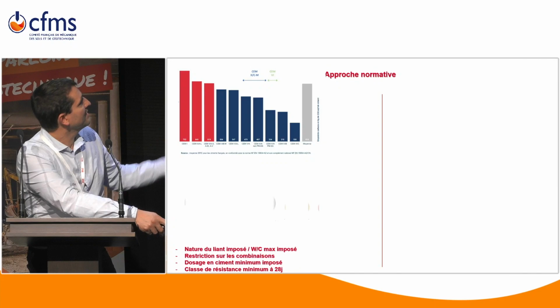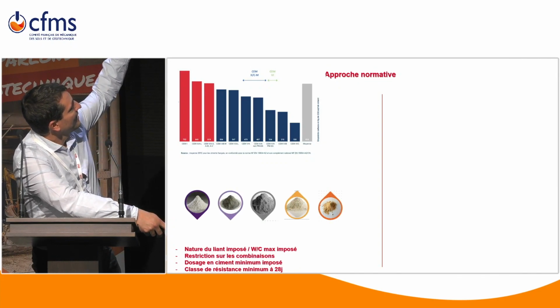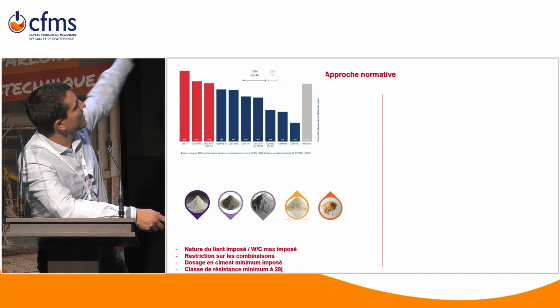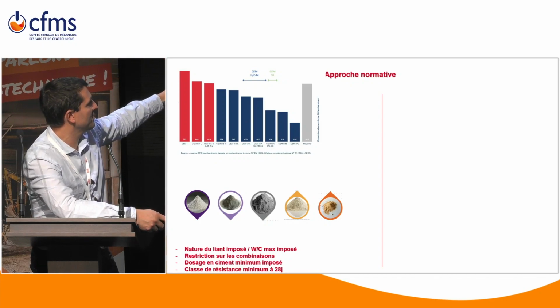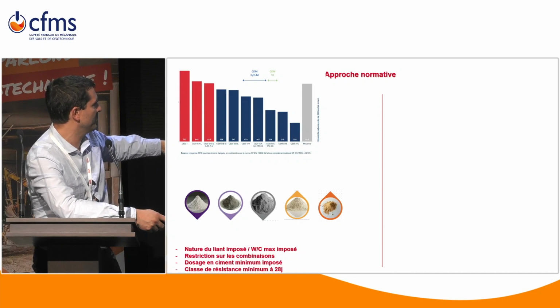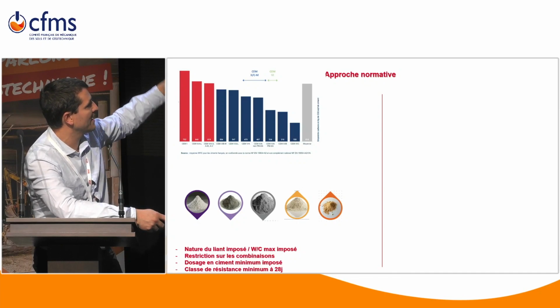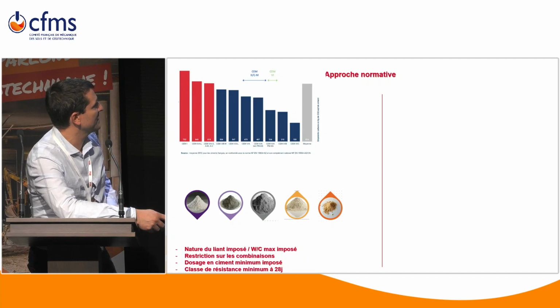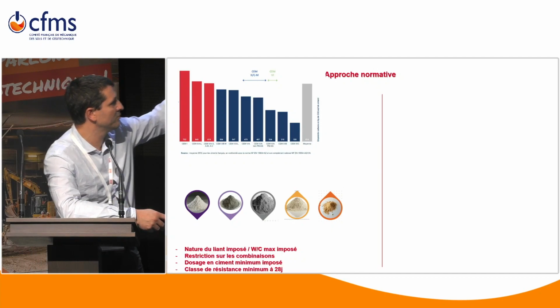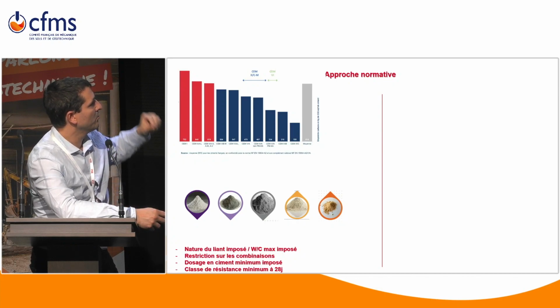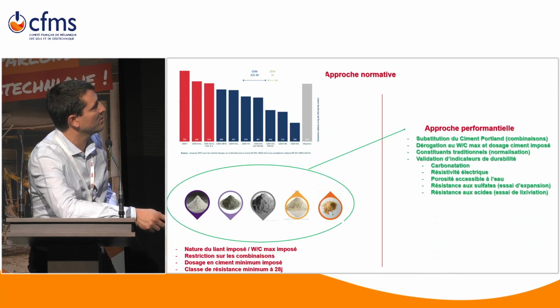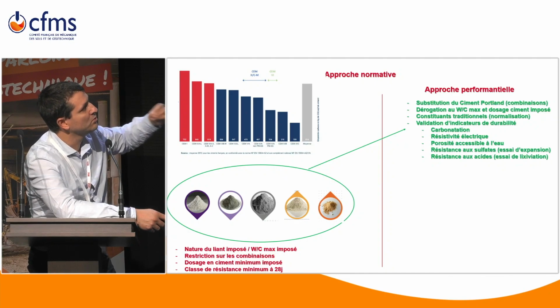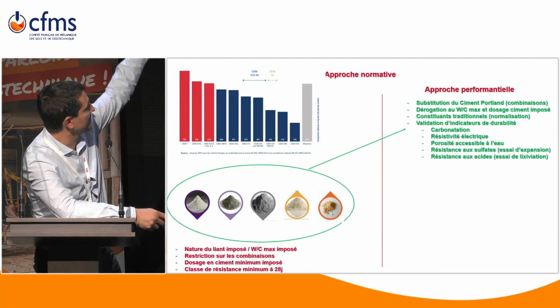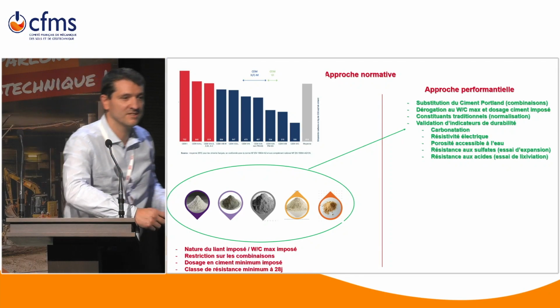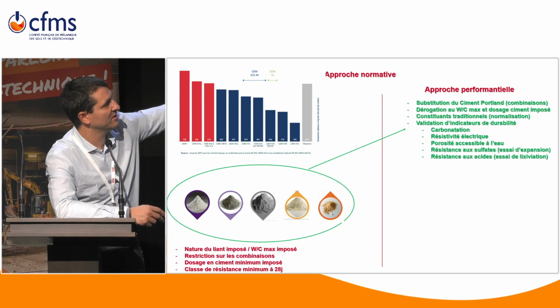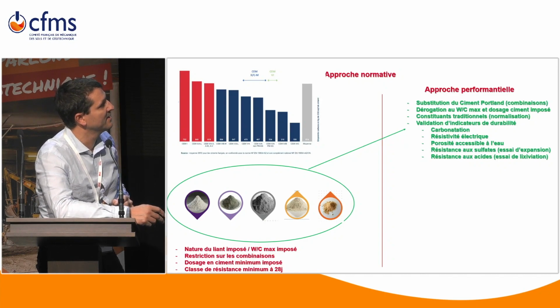Okay, so just to emphasize the interest: normally we can use the normative approach. We have a range of cement, but the binder content is imposed, the water cement ratio is imposed. There is restriction on the replacement that we can use, all those cementitious materials like slag, fly ash, silica fume, calcined clay, limestone filler. We have limitations. Now with the performance-based approach, we have much more room to play on the replacement of standard cement with those additions, and it allows you, through validation of a durability indicator, to build a new mix design.